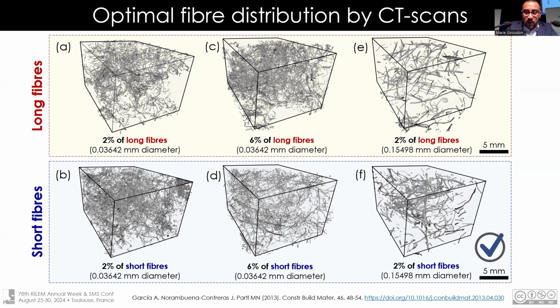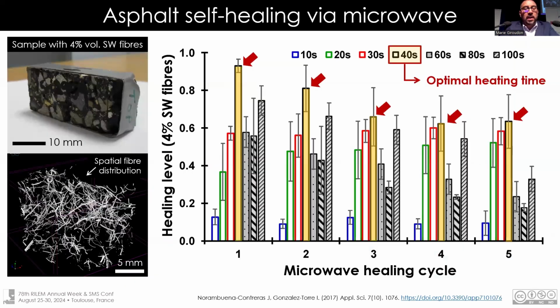The recommendation after evaluating 1,000 tests is to use short fibers in a low addition percentage with a diameter close to 0.2 millimeters. On the other hand, it is also necessary to evaluate the heating time of the sample by using microwave radiation in order to compare with induction technology. Thus, the effective amount and optimal times allow us to compare microwave radiation with induction heating.